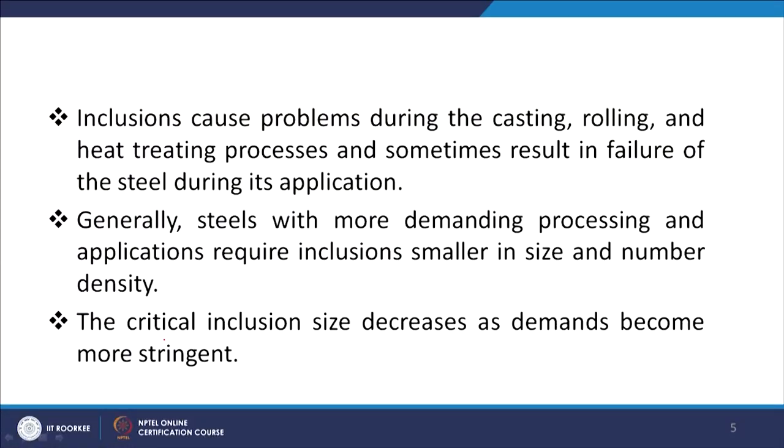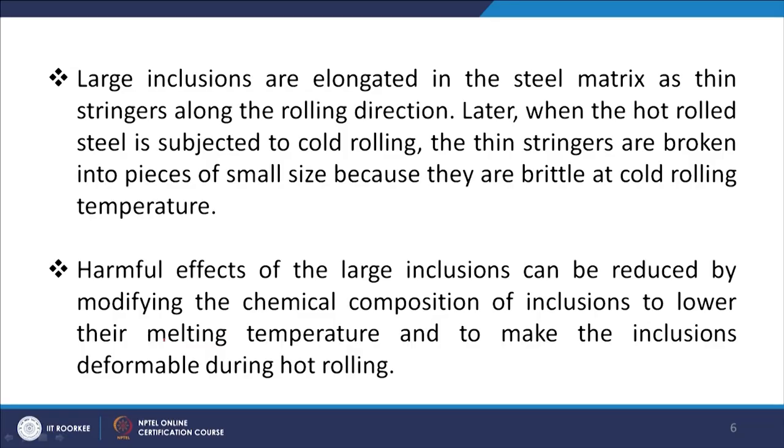Demanding processing and applications require smaller and fewer inclusions. Critical inclusion size decreases as demands become more stringent — the end user will specify that inclusions should not exceed a particular critical size. Larger inclusions present in the steel matrix will be elongated as thin stringers along the rolling direction.